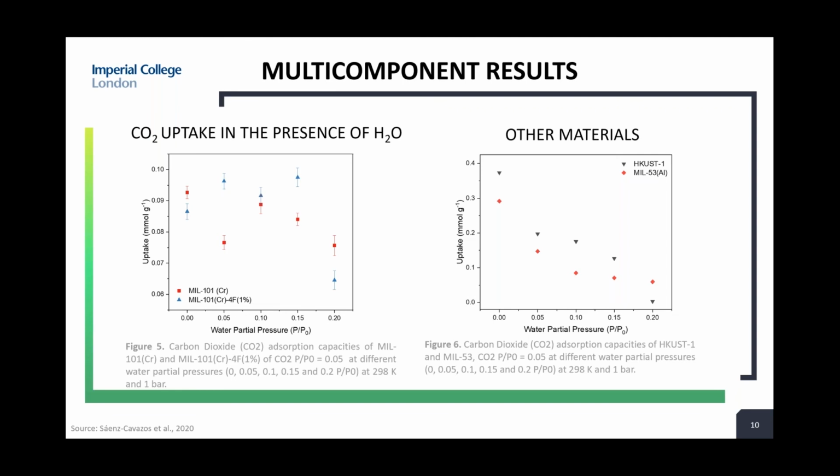However, there's a value of relative humidity where the presence of water molecules no longer has a positive effect, and rather these molecules compete for adsorption sites with CO2. This phenomenon has been previously reported for other MOFs, such as MIL-100 and UiO-66. So it's important to mention that the CO2 uptake of the materials studied is not exceptional under real industrial conditions.